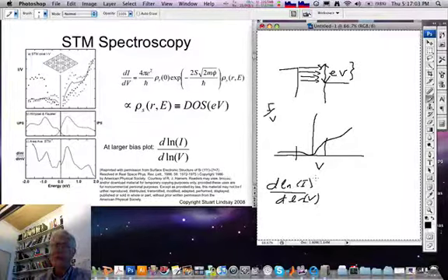The point here is that these measurements are made not on a bulk surface, but on atomic features on the surface. And what the top plot shows is a spatially resolved spectroscopic map of states on the silicon 7x7. This is work of Bob Hamers, who pioneered the atomic resolution spectroscopy of electronic states on surfaces using a scanning tunneling microscope.